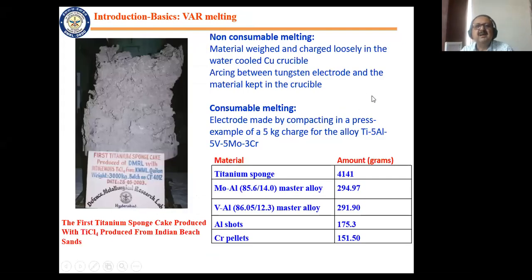So now I talk about melting, although I'll not talk about it in detail. Now, this is one of these titanium sponge, which was first made in DMRL. As you know, it is produced by Kroll's process, where titanium oxide is converted to TiCl4, and that is reduced by magnesium, which is driven out, and then you get a cake like this, which is known as a titanium sponge, and then this is crushed to get titanium sponge. That is the starting raw material.